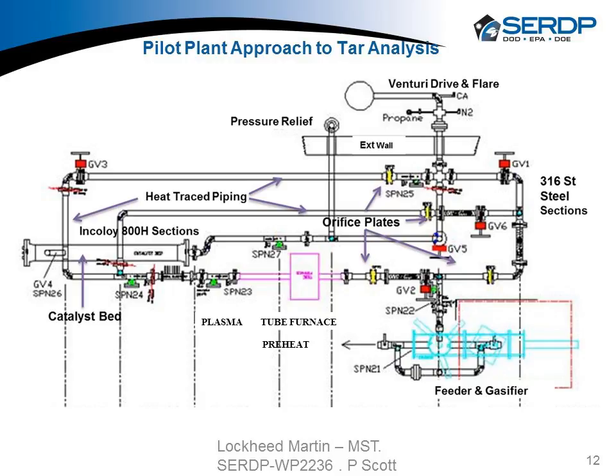Nitrogen was added so that, if we had some kind of emergency shutdown failure, we would pump nitrogen into this. If this is at a vacuum, we've got a fuel mixture going through this pipe. If we suddenly lose the Venturi or something shuts down, we're going to be potentially drawing a flame plus air into a fuel mix. So we thought that was a good idea. And then we did have pressure release throughout the system going to the exit, out through the exterior wall.